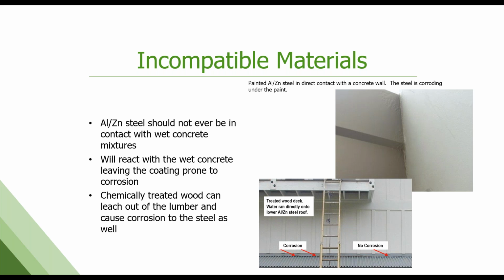So that's a problem. Chemically treated wood is another one we encounter. Chemically treated wood usually uses some kind of copper mix or copper chemical to treat it. That copper can leach out. It's incompatible with galvanized and Galvalume products. And if it's allowed to drip or run onto the painted panels, it will cause premature corrosion. An example there is a wood deck that was chemically treated, and that's just running off onto the metal roofing below it, causing issues. As soon as you got out from underneath that deck, the panels were fine. Next slide.